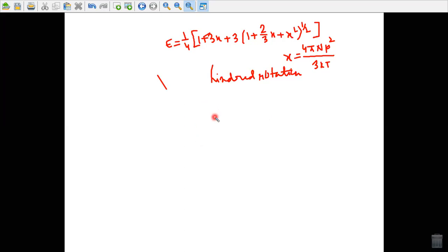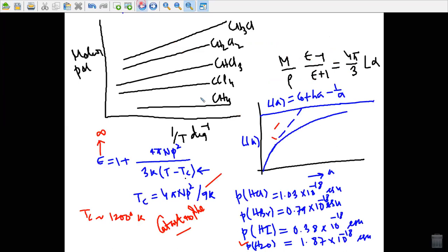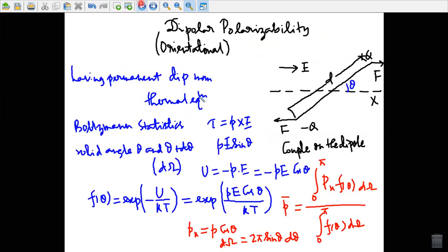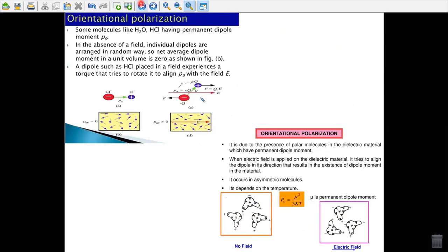The prime example is liquid water, where every water molecule is a little dipole that can have any orientation with respect to other molecules. Moreover, the orientation changes all the time because the molecules move. So orientational polarization for dielectric dipoles is pretty much limited to liquids, but we will encounter it in a major way again in magnetic dipoles.